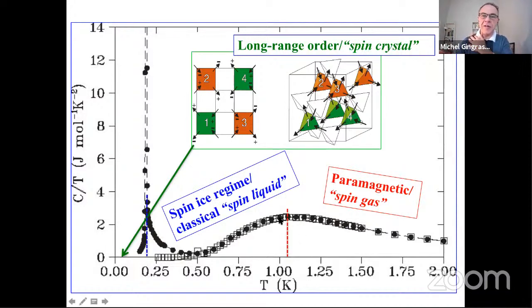Once you cool down the system and you reach a temperature of the order of the Curie-Weiss temperature, the system starts to develop correlations, but without developing long range order. It crosses over from a trivial paramagnet to a correlated state. It's really a classical spin liquid. There's no quantum mechanics here, but there's no long range order. It's a very constrained state where the spins on each tetrahedron must obey the two in, two out ice rules. And the bump in the specific heat is a signature of a rapid drop of entropy, where you go from 16 states per tetrahedron to only six available that obey the ice rules. So it's a crossover from a paramagnet to a spin liquid without a transition.